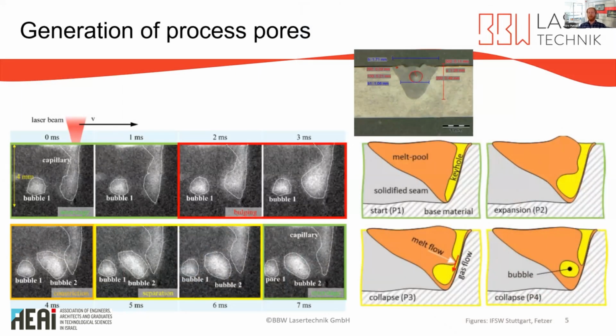We have seen already very nice theoretical and practical views into laser deep welding, so I can skip some things. With laser deep welding, a zone of vaporized material, the so-called vapor capillary or keyhole, is created in the laser-matter interaction area due to the higher intensity of the radiation. The stability of the keyhole is maintained by a pressure balance of various acting forces in the material and the defined processing speed. The liquid melt flows around the open keyhole and finally solidifies as a joining weld metal behind the moving laser beam when cooling down.